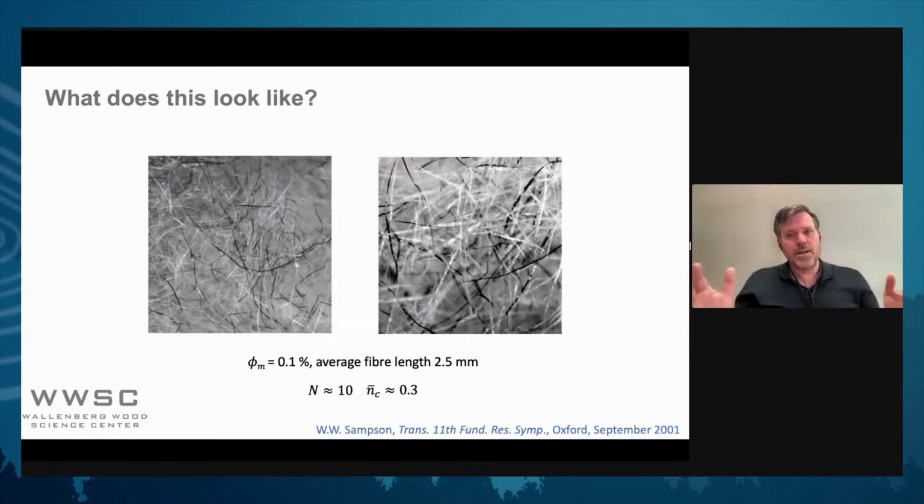And they are clearly below the connectivity threshold because contact points are less than 2, but they are still forming a network. And the reason is the elastic properties, the semi-flexibility of these fibrils make them get interlocked into a system at much, much lower concentration than you would if you have perfectly stiff fibers.